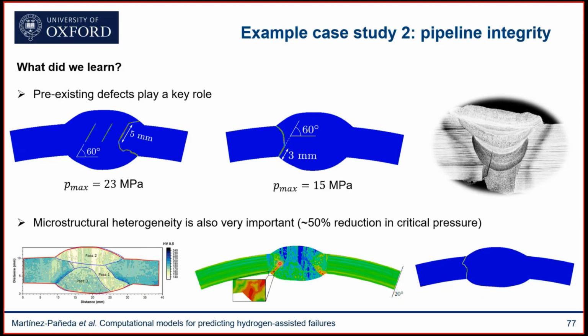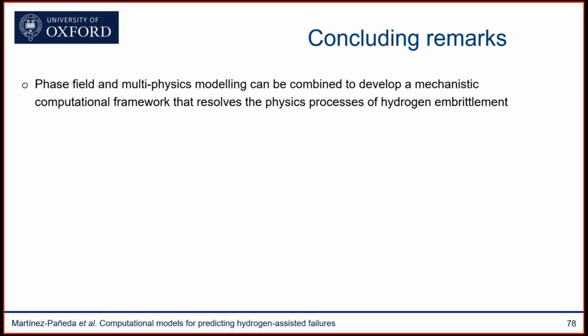So we can have, for example, these small, thin regions of harder material, which are more susceptible to hydrogen. And when we account for these things, we see a 50% reduction in critical pressure. So microstructure does play a role in this aspect. That's all. That concludes my talk, with a few last-minute concluding remarks.